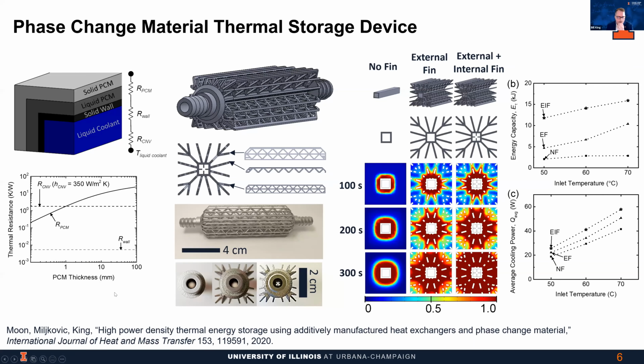Okay, so if we just look at the very simple thermal model of how such a device might work, in fact, it is the thermal resistance within the phase change material that limits the cooling power and limits the overall energy that can be stored in the phase change material. And so by having this highly finned device, we can promote higher heat transfer rates, higher cooling power, and overall access more of the phase change material in the vicinity of the device.